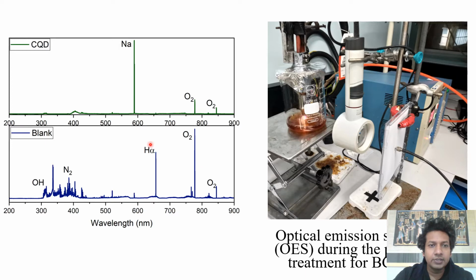This one is taken during a plasma treatment into water. You can see the H-alpha line indicating atomic hydrogen, and hydroxyl here. So we can assume that water dissociation is taking place, and there are some nitrogen lines and oxygen lines here. This one is taken during a plasma treatment of PTSA sodium salt. Sodium gives an intense yellow signal which pretty much outshines all other peaks except these two oxygens.